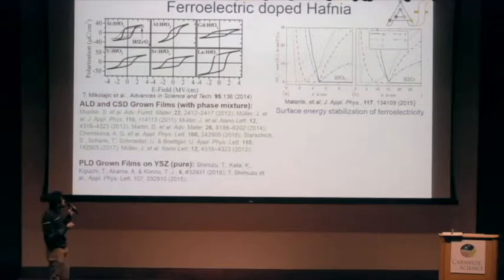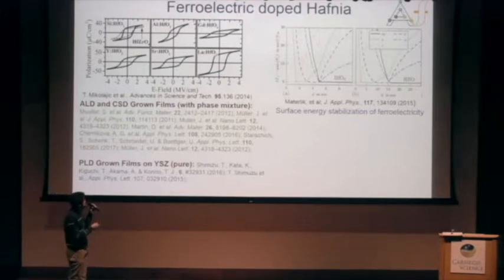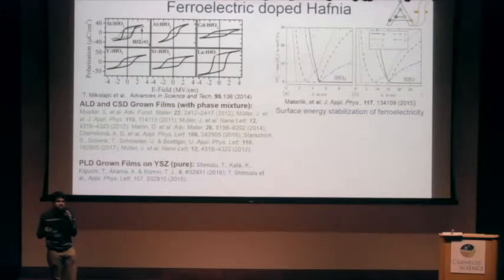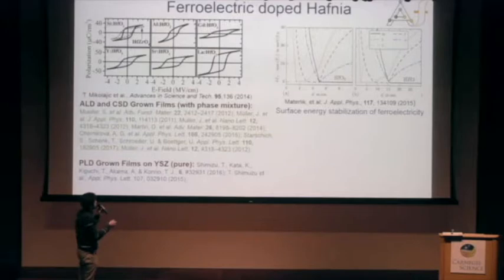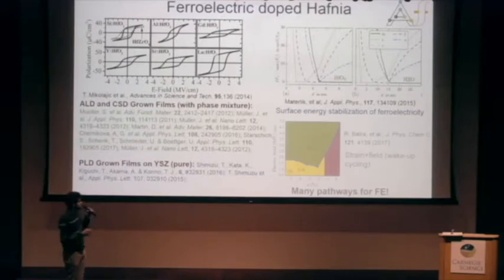And here, for instance, in this paper from Munich, they consider surface energy of these small nanoparticles to be a stabilizing factor for this polar orthorhombic phase. And then they, in fact, determine, for example, this red curve gives the energy stability of the ferroelectric phase, and it is stable in certain, say, size ranges, depending on the composition of the material that they're looking at.